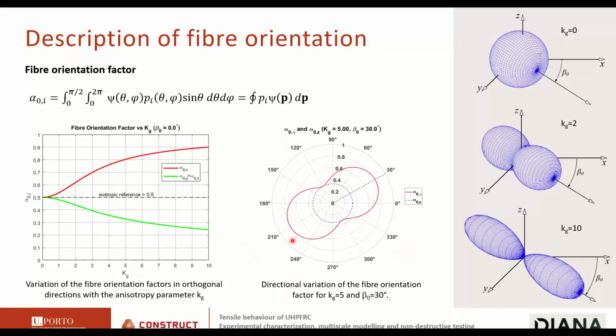So here it's another very interesting picture which shows us the following. Using Kg equal to 5, corresponding to this line here, I'm showing here the value of the alpha, of the fiber orientation factor, along any direction. Okay, here I use as preferential direction of fiber orientation 30 degrees. So you see the maximum value of the fiber orientation occurs here at 30 degrees. But then if you go away from this 30-degree alignment, you see that the fiber orientation factor is decreasing its value. Here, the fiber orientation factor is given by the radius. So this is a polar plot.